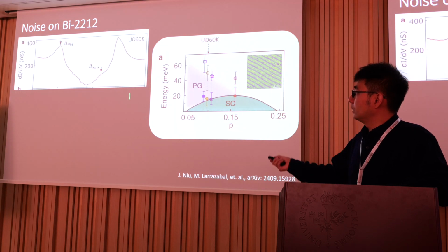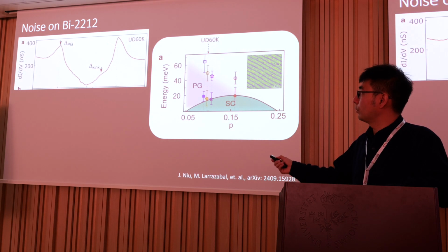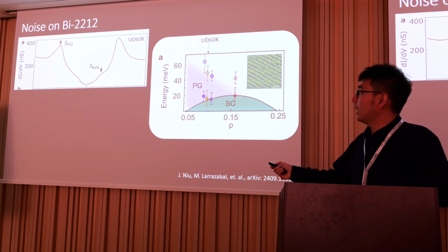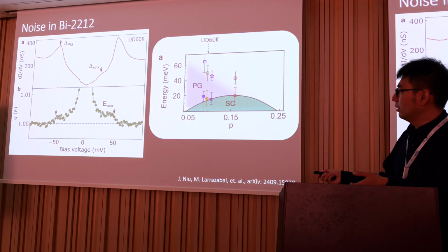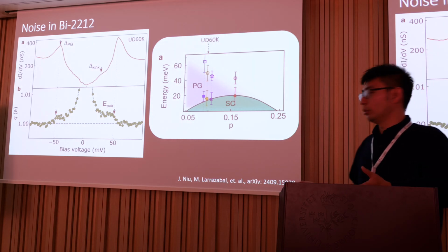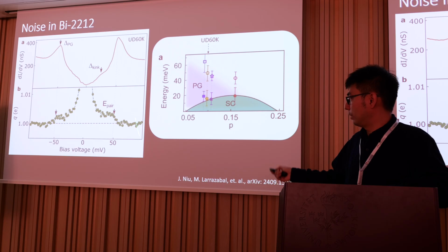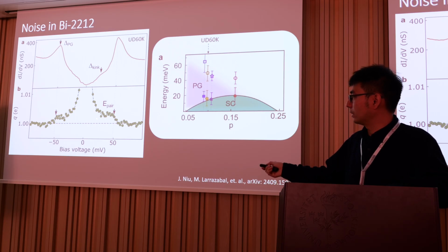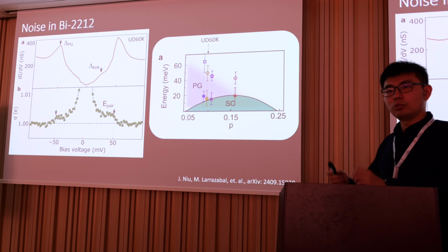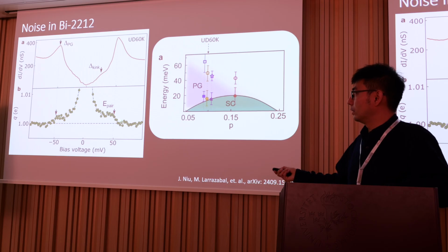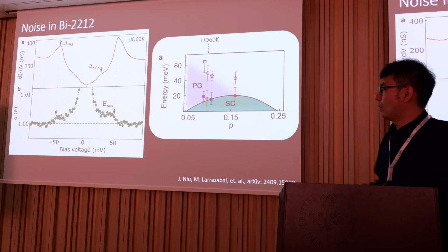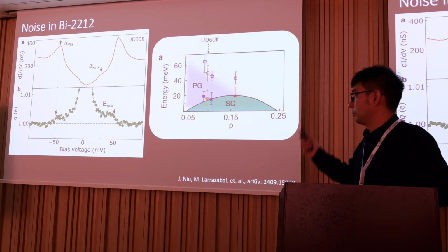First, this is the spectrum. It's a typical spectrum. We have the pseudo gap and the superconducting gap. And this is the noise. You can clearly see that first, we see this step. You can clearly see that it does not fluctuate around 1e, instead it increases in a step. So this means that with our very good resolution, we can measure the noise enhancement successfully for the first time. And the value is a little bit smaller than 1%. It's similar to what we expected in simulation.